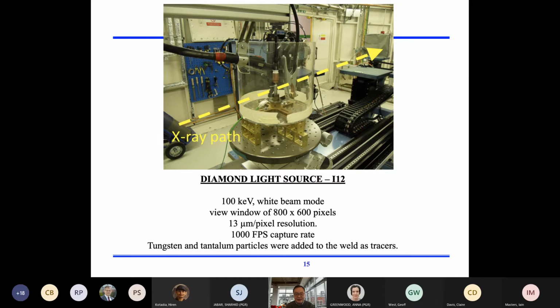In these experiments, we also use particles to trace the internal flow. The particles we chose were tungsten and tantalum. We added particles, but in the end we selected tungsten. Tungsten can stay a longer time in the weld pool compared with tantalum.